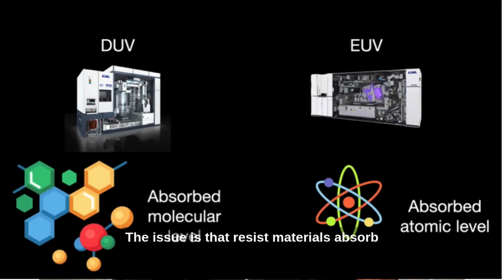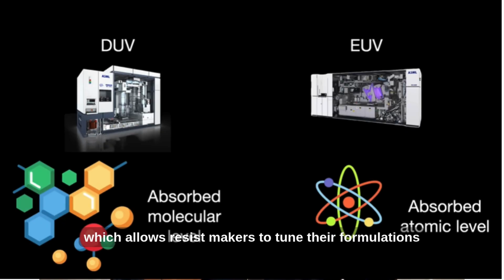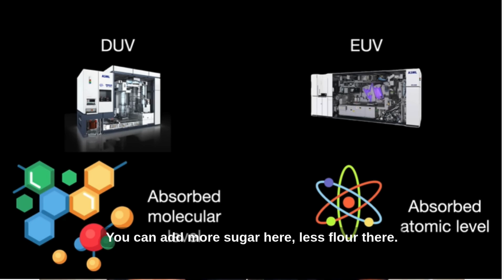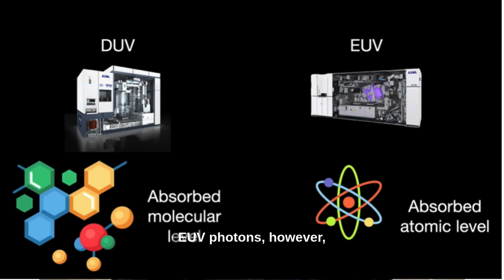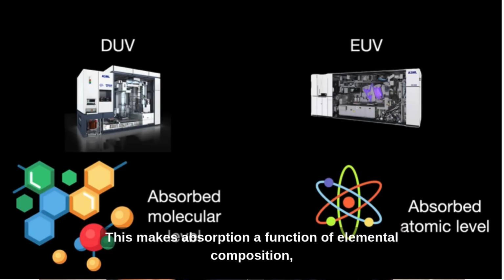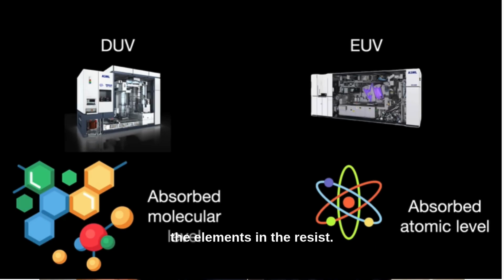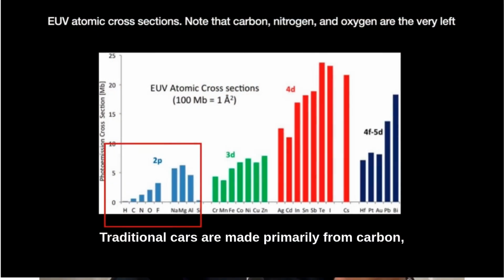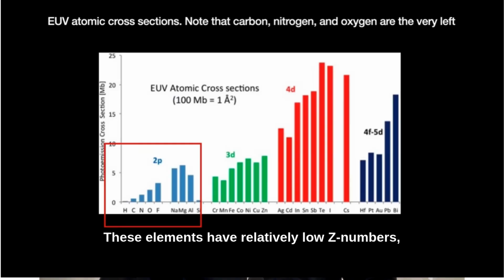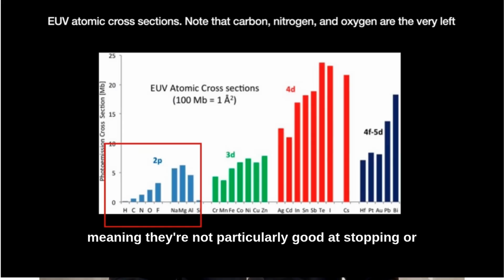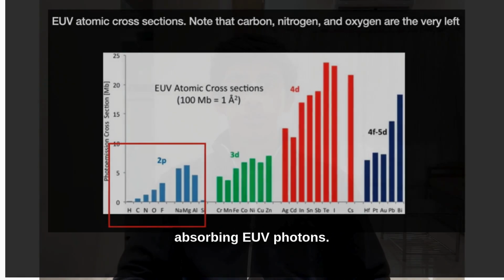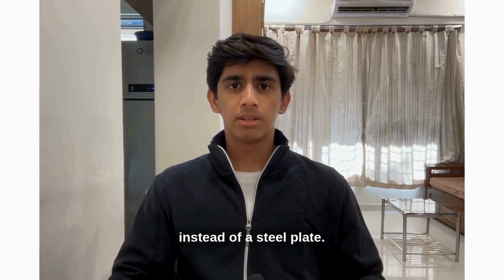The issue is that resist materials absorb DUV and EUV photons in fundamentally different ways. DUV light is absorbed at a molecular level, which allows resist makers to tune their formulations by adding or removing specific molecular groups. It's like adjusting the recipe for a cake. You can add more sugar here, less flour there. EUV photons, however, interact with matter at an atomic level. This makes absorption a function of elemental composition, specifically the atomic number or Z number of the elements in the resist. Traditional CARs are made primarily from carbon, hydrogen, and oxygen. These elements have relatively low Z numbers, meaning they're not particularly good at stopping or absorbing EUV photons. It's like trying to stop a cannonball with a piece of paper instead of a steel plate.